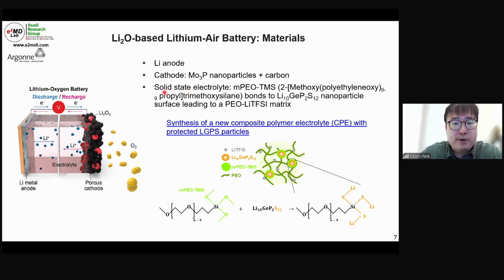In this research, Larry and Mohammad came up with a unique composite polymer electrolyte-based solid-state electrolyte by adopting the mPEO-TMS. This is the full name of this material. We call this MPO only. And also the LGPS, the lithium, germanium, phosphorus, and sulfur. So this is one of the most popular sulfur-based solid electrolytes.